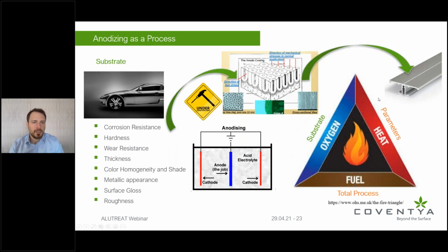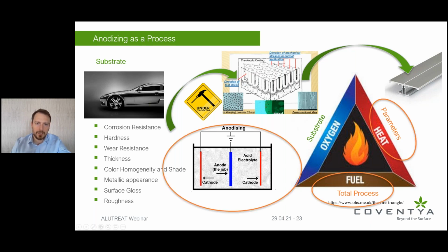So as Coventya, what we like to emphasize is that anodizing is not just related to the chemistry. And we like to use this schematic look of a fire triangle, where you have on one side your substrate, and then you have the parameters and your total process in order to get to the right oxide layer, as it is possible to see here. But in essence, one of the biggest contributors to our process is the effect of the substrate, as we briefly mentioned, which is generally governed by the alloying element.